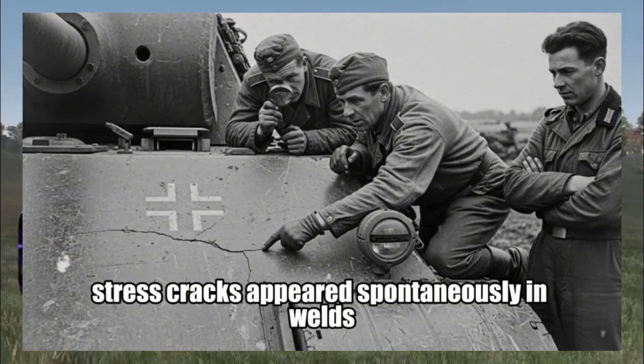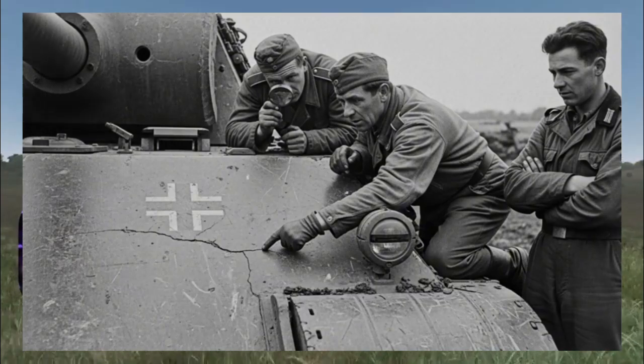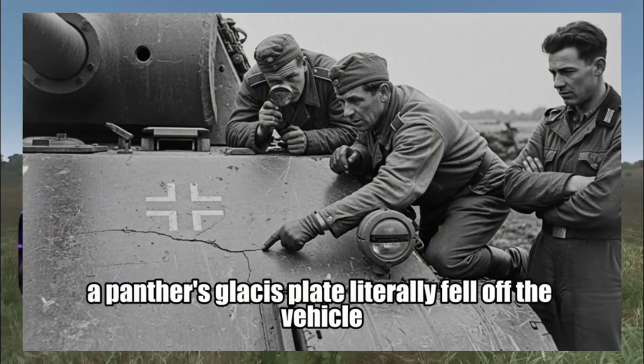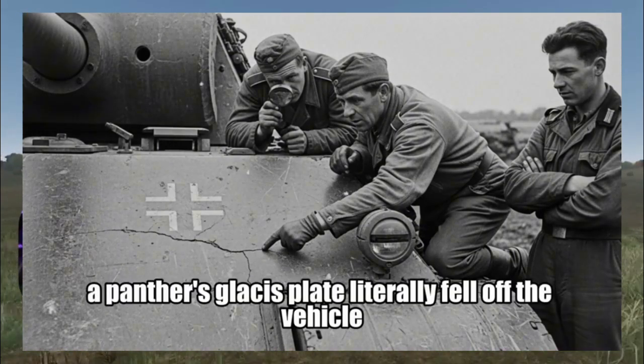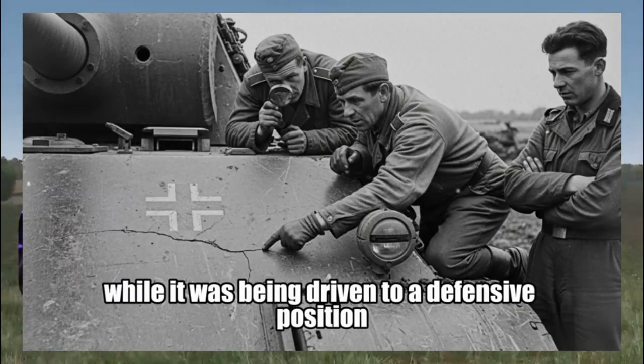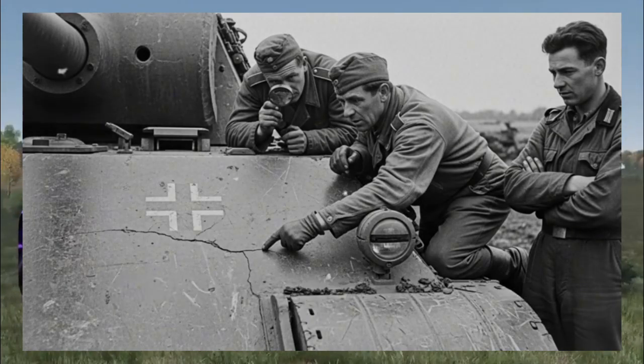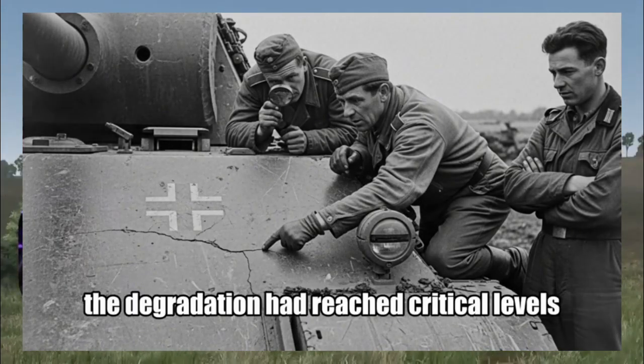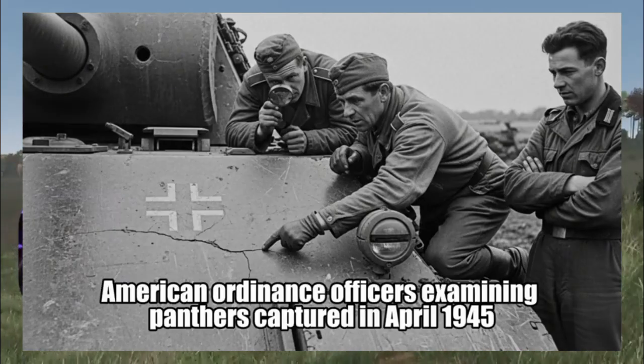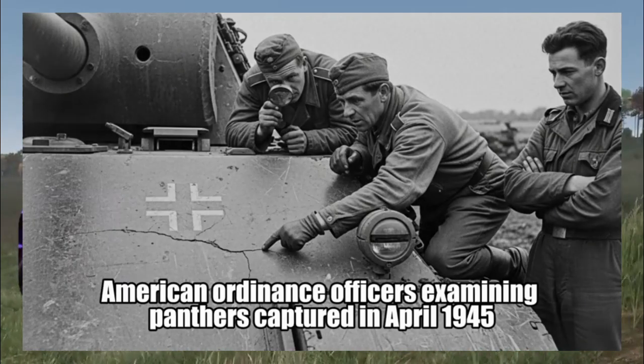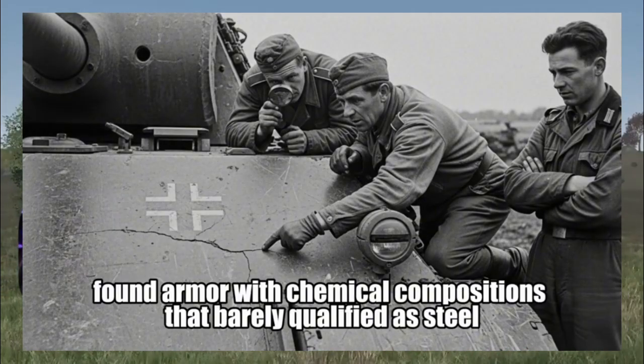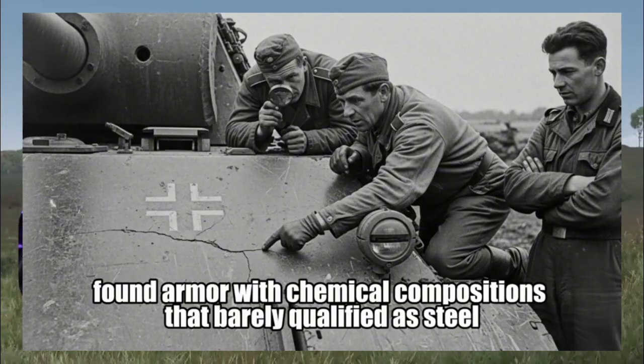Stress cracks appeared spontaneously in welds. In one documented case, a Panther's glacis plate literally fell off the vehicle while it was being driven to a defensive position. The degradation had reached critical levels. American ordnance officers examining Panthers captured in April 1945 found armor with chemical compositions that barely qualified as steel.